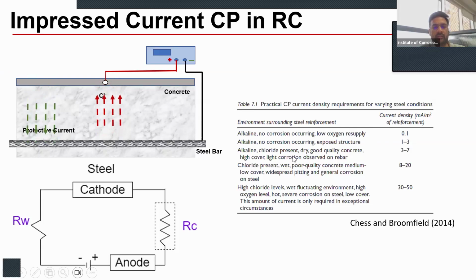When concrete is still alkaline, but chloride starts to present, the concrete is dry, and cover is good quality, about 3 to 7 milliampere per meter square of current density is required. However, when chloride is present in higher quantity and the concrete is typically very poor quality, we need a much higher current density for the protection.